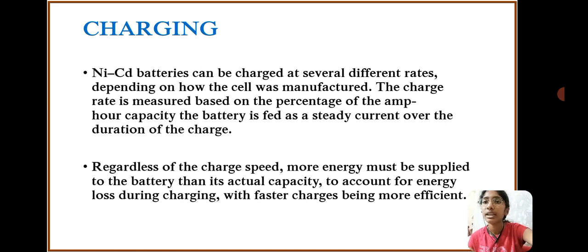So nickel cadmium batteries can be charged at several different rates depending on how the cell was manufactured, so the charging capacity depends on the manufacturer's model itself. The charge rate is measured based on the percentage of amp-hour capacity. The battery is fed a steady current over the duration of the charge. Regardless of the charge speed, more energy must be supplied to the battery than its actual capacity to account for energy loss during charging, with fast charges being more efficient.